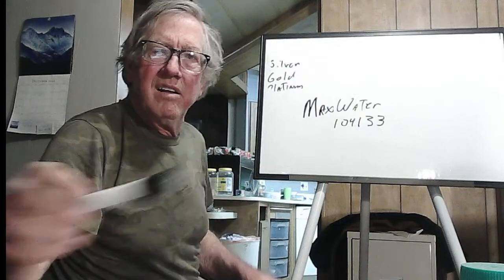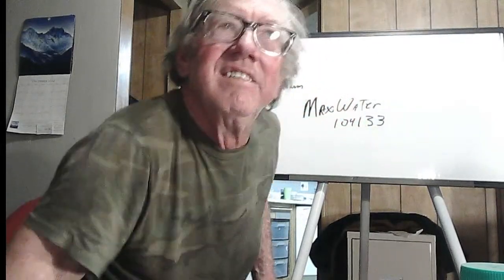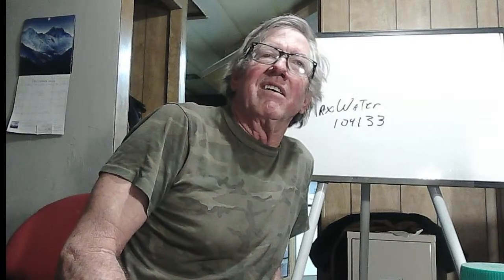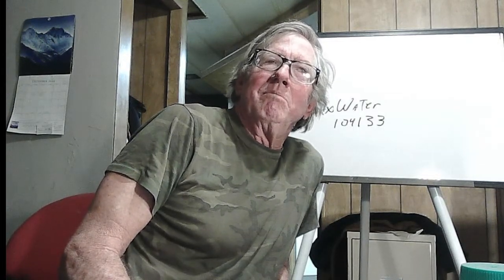And where did we get the Max Water from? Direct from Max Water, on the internet. We got the resin direct from Max Water. It's on the internet, and the number we use is 104133. Then we use a stripping circuit to get it off of the resin. That's thiourea and battery acid. And then an electroplating cell. It's pretty minimalist.